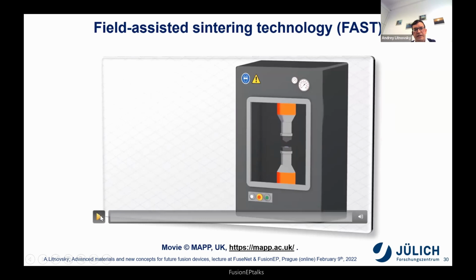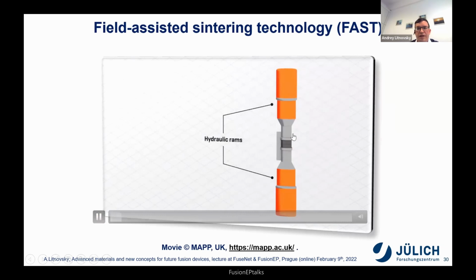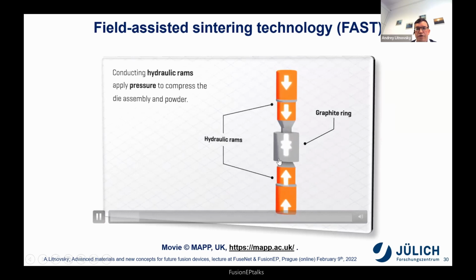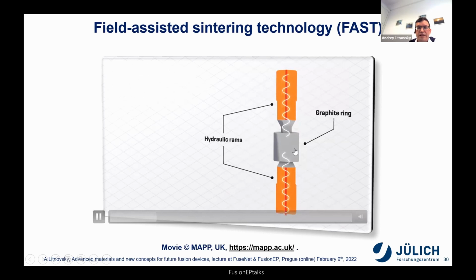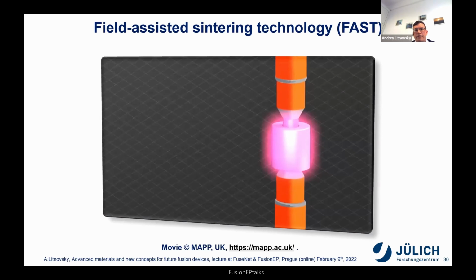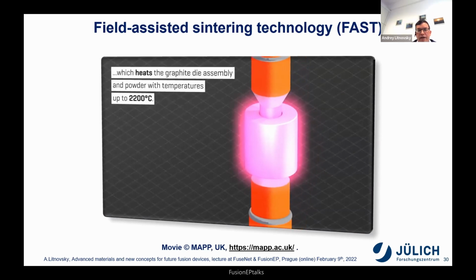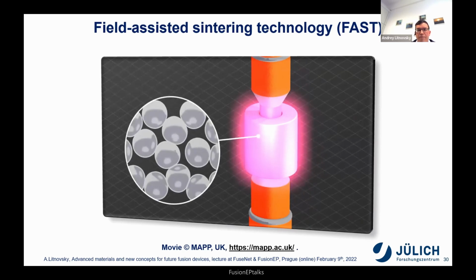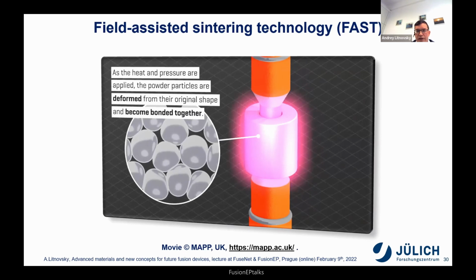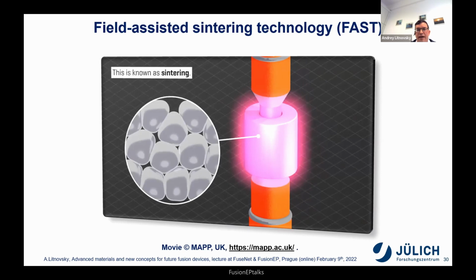In field-assisted sintering technology, there is one effect which comes on top. You press the powder inside, very nicely isolated, and start pressing. This is like the usual technology. And now comes the game changer. In field-assisted sintering, you are really pushing a pulsed current through the particles. And this allows us to heat the powder very efficiently and to melt, at least, or deform the boundaries of the powder particles.